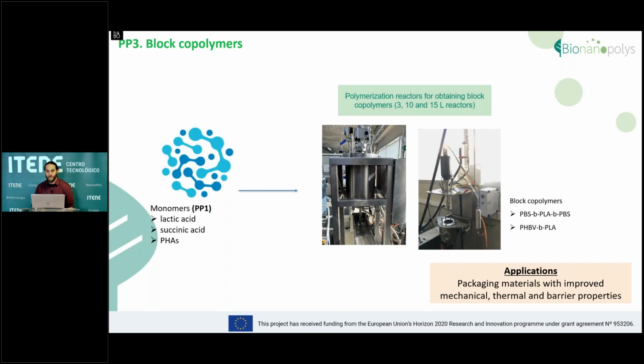On the other side, from the monomers we collected from pilot plant 1, like the lactic acid, succinic acid, and the PHAs, we can convert them into block copolymers in our condensation reactors. We have different ones available from 3, 10, or 15 liter reactors. And these block copolymers could bring improved barrier properties for biopolymer composites.